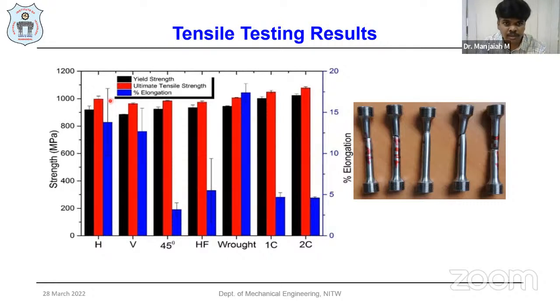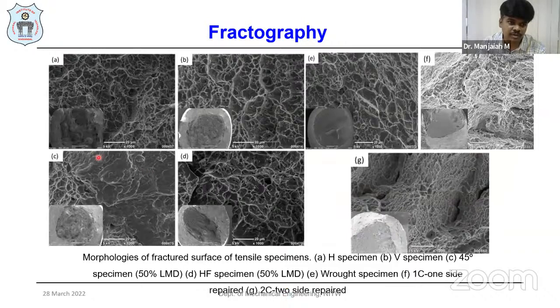The ultimate tensile properties and yield strength are very good compared to the wrought alloys. But we are only getting lower elongation, the ductile properties, because of the porosities or defects. You can see these kinds of porosities, defects, and lack of fusions. If you see the wrought alloys, they have the better ductile properties, and this one is the wrought specimen.